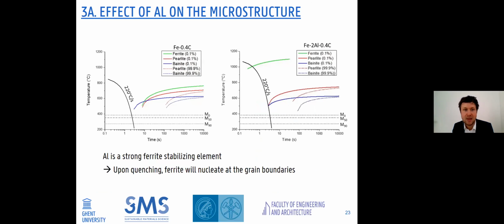And the reason for this can be found in the continuous cooling diagrams based on models of Kirkaldy and Bhadeshia, showing that indeed at a quite fast quenching, 220 degrees per second, we crossed the ferritic nose in the case when aluminium was added. So aluminium, as a strong ferrite stabilizing element, upon quenching will nucleate at the grain boundaries. And this, of course, has an effect on the failure and also on the ductility and strength of the materials. These CCT diagrams took into account the chemical composition, the austenitization temperature, and the prior austenitic grain size.